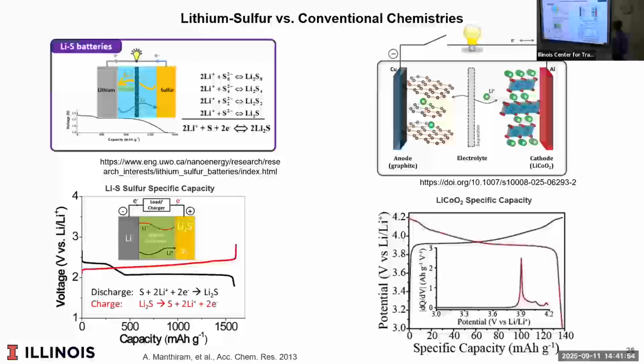And the difference is in here, basically, in a lithium sulfur battery, you have pure lithium that stores energy. You have pure sulfur that stores energy. Here, I have one lithium and about 20 other atoms that do nothing. And so that's sort of the take home here. And the difference is the capacity here is thousands of milliamp hour per gram versus hundreds of milliamp hour per gram. So someday we might be there.